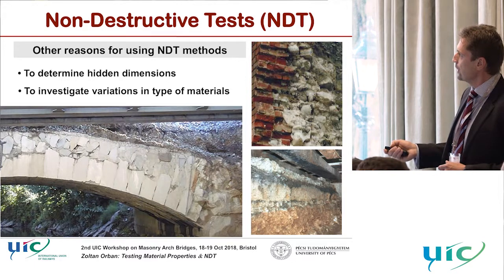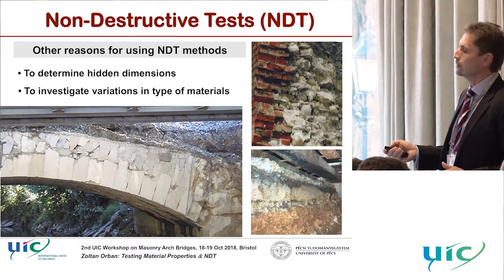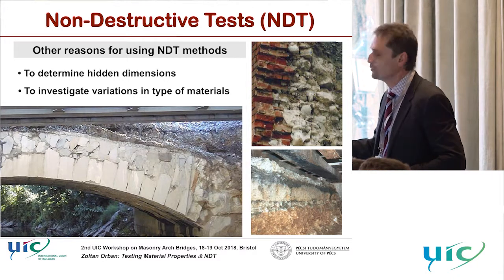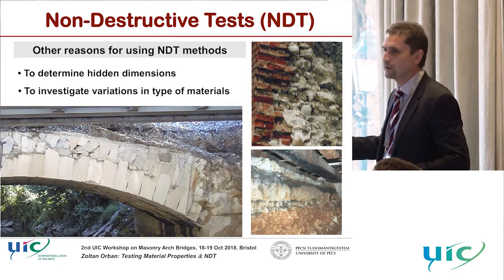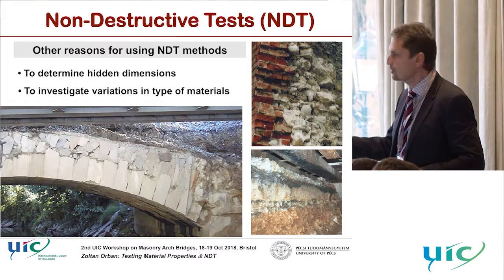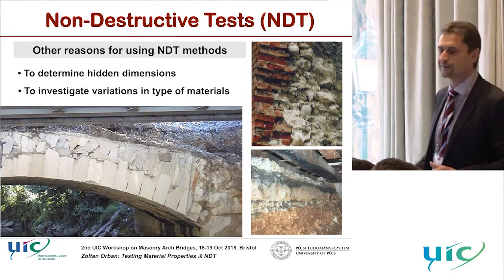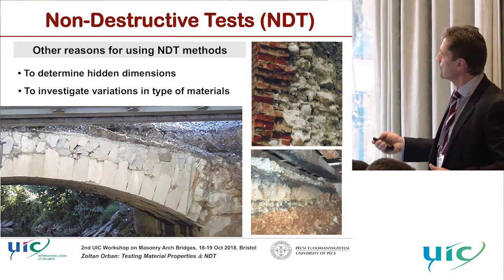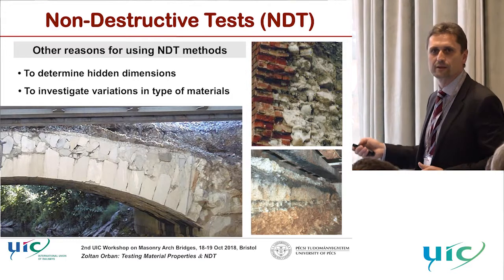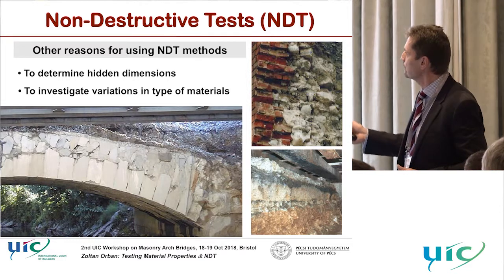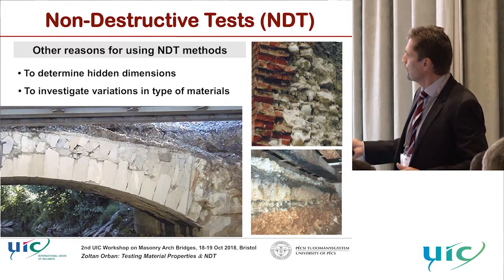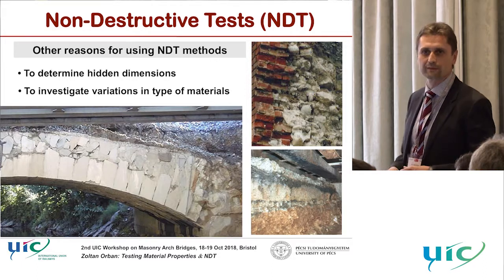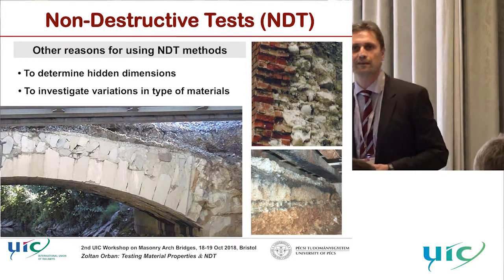NDT can help investigate variations in the type and condition of materials. In one example, the condition of stonework varied throughout the arch thickness — good condition on the outer part and bad condition inside — meaning only the outer part can be relied upon to carry the load. We also often lack information on what is in the fill material or what layers are present in the fill.